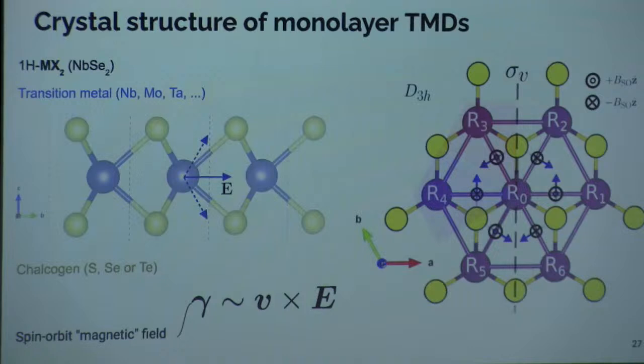The origin of Ising spin-orbit coupling is fairly straightforward to understand. Here I show the crystal structure of niobium diselenide. The vertical lines divide the unit cells, so you see that each unit cell has a niobium atom and two selenium atoms. Most of the electronic weight comes from the niobium d orbitals, but the d orbital electrons feel a crystal electric field coming from the selenium atoms, and this electric field points strictly in the out-of-plane direction. And if you remember electrodynamics, if transport is in the plane, then v cross electric field gives you a spin-orbit magnetic field, which points strictly along the z-axis.